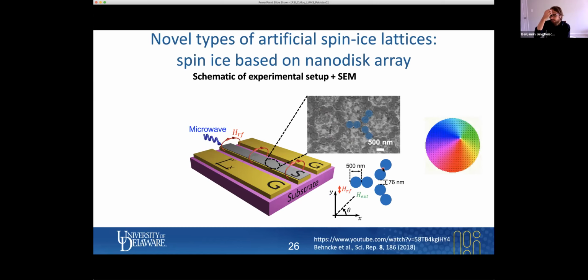Now, we got interested in this kind of structure because in disks at low magnetic fields, you get something called the formation of a vortex core. And these vortices can be driven in the sub-gigahertz frequency range, and they then describe a gyrotropic motion, which you can see in this animation here. So the idea was, well, we could combine in the low frequency regime this gyrotropic vortex motion, and if we saturate the disks, we could observe spin waves in the system. So let's see how this turned out.